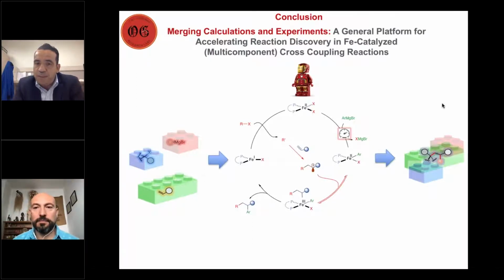But so far, the pre-catalyst does not have much of an effect in terms of the yield, the efficiency, very minor, but it does have an effect on some of the selectivity that we see, and that's still ongoing. But yeah, I agree that it could definitely change the formation of different iron species. And Mike Neidig has done some preliminary mechanistic studies on that, where they show the pre-catalyst does have an influence in terms of the rates of transmetallation. So I think in a sense that could change this catalytic cycle shown here.